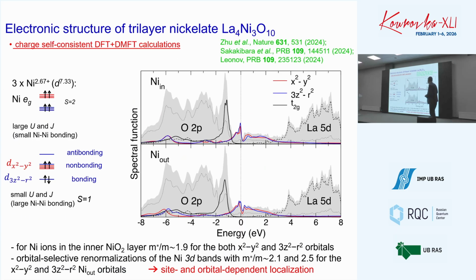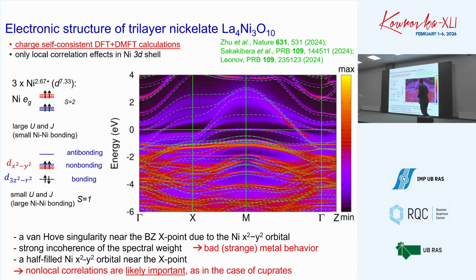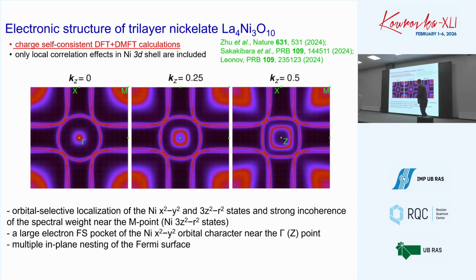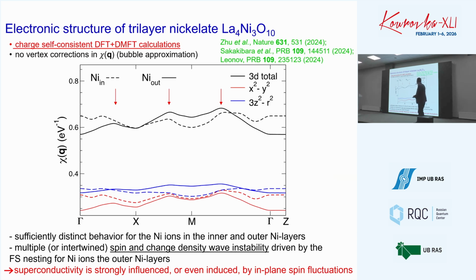Yes, and this is a 3-layer system. I would say the physics is essentially the same. The only thing is that we have somewhat different bonding states here, the bonding splitting. Now we have two singularities due to the top layer and bottom layer. Fermi surfaces are nearly the same, although we do see some kind of three-dimensional-like Fermi surface around the gamma-z direction. The top and bottom layers show behavior like in the bilayer system, although the central one is less correlated and somewhat more, I would say, frustrated. There is no clear magnetic state.